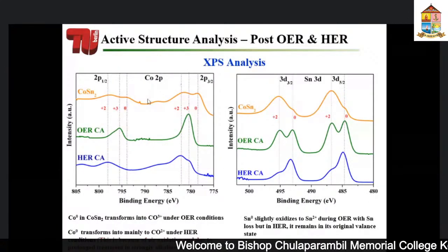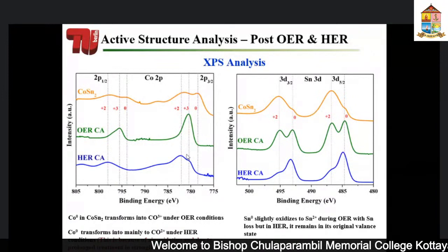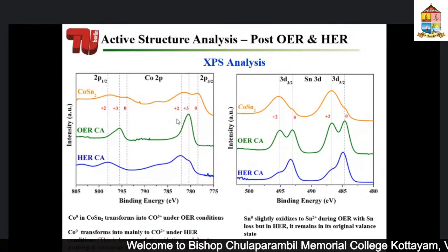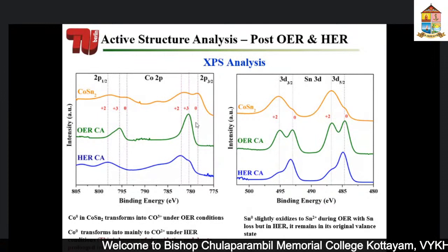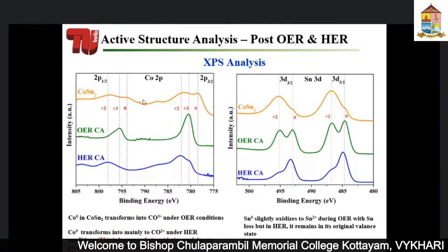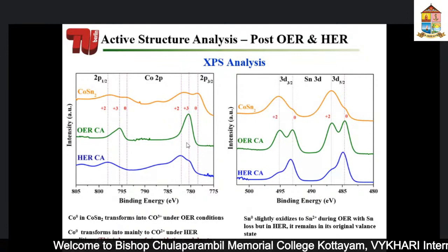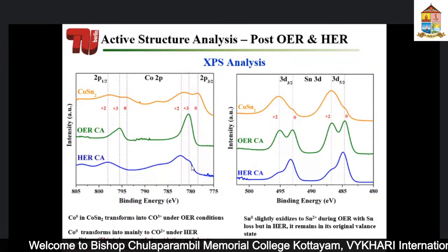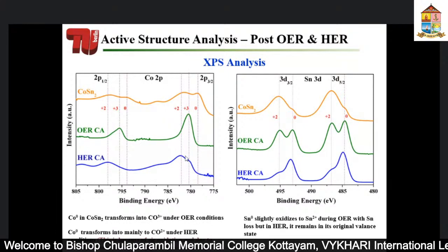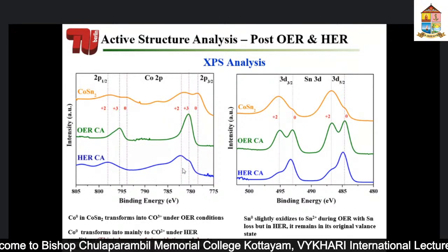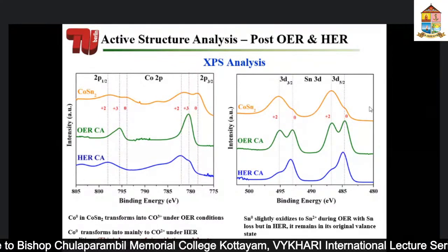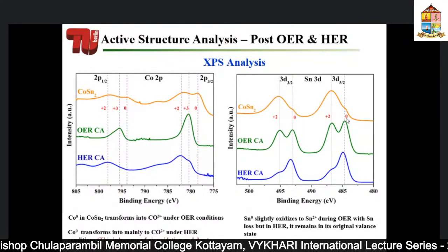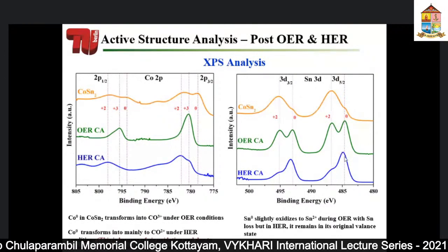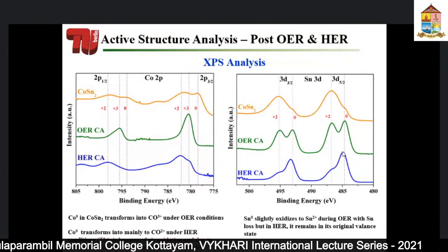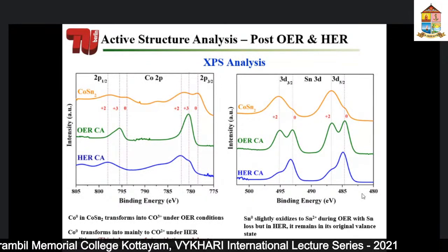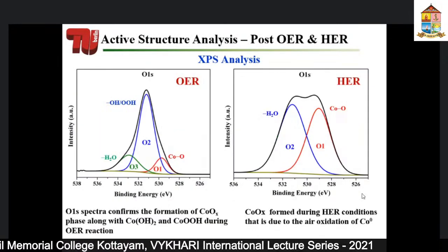Okay, we also investigated this by X-ray photoelectron spectroscopy. And again, it's not a surprise that if you take the oxygen evolution reaction, your material oxidizes completely to 3+, which is needed to drive the oxygen evolution reaction. And in the case of the hydrogen evolution reaction, it didn't change much. Only what you see is the oxidation peak, which is responsible for surface passivation. Same situation here. You preserve your tin, and also in the case of HER, you have a very nice peak for your tin 0. That means your material didn't change much.